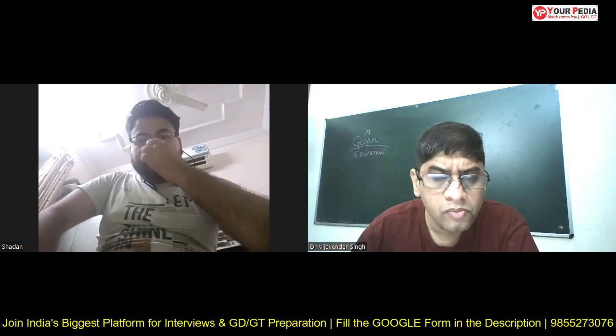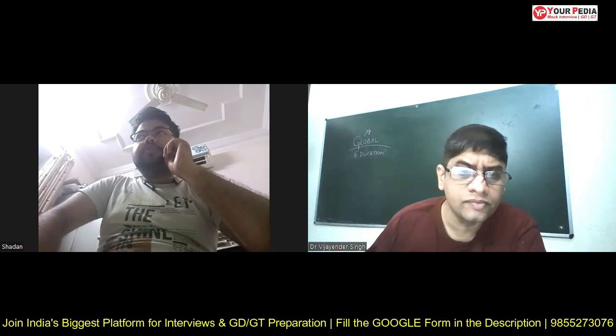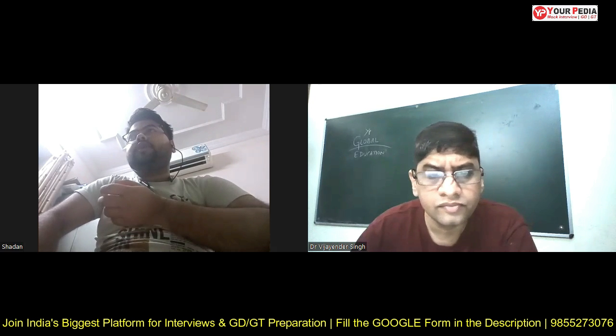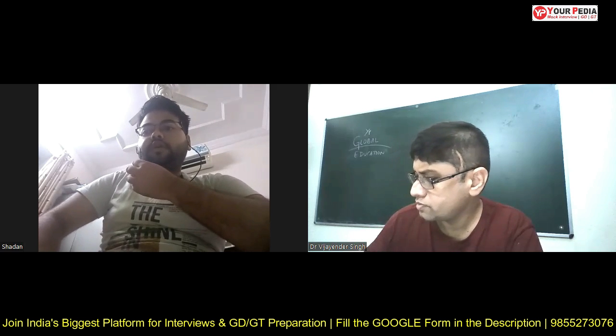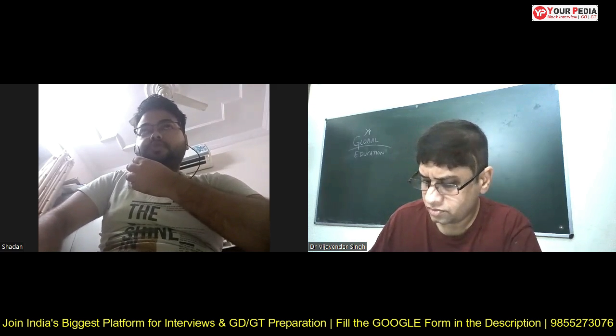Yes, sir. The Bayer process is the process of leaching of alumina. It means the alumina is reacted with concentrated caustic soda solution at a temperature of 110 to 220 degrees Celsius, and a high pressure is applied, 20 to 25 atmospheres. So sodium metaluminate is formed. This sodium metaluminate will undergo hydrolysis to form aluminum hydroxide.